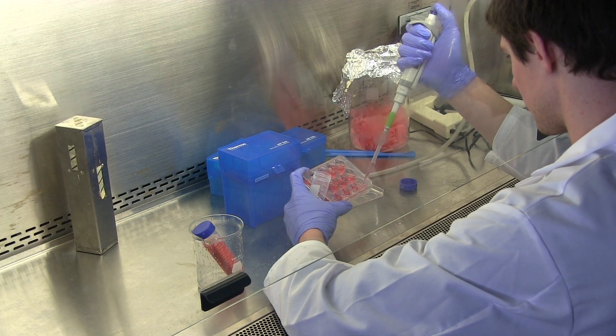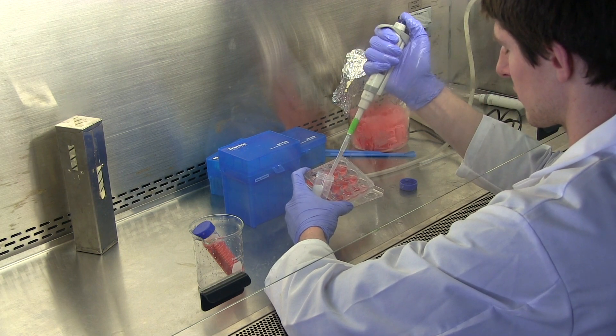But one of the major limitations of most injectable hydrogels is a lack of pores. So even if it's applied to damaged tissue, the neighboring cells of the host cannot migrate into the hydrogel because there is no pore to get into. The significance of our invention is that we came up with a method to make an injectable and highly porous hydrogel, and the method is extremely easy, involves minimal chemistry, is very cost effective, and at the same time is highly bio-functional.